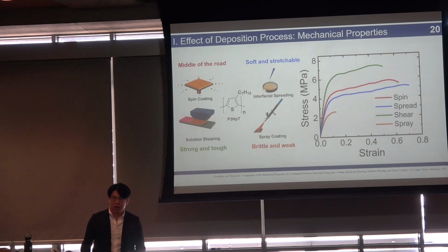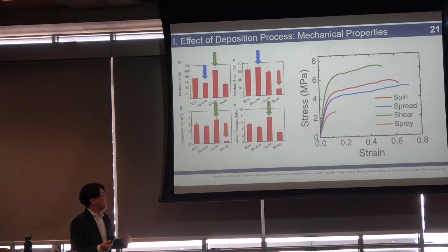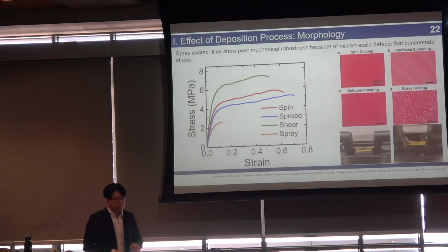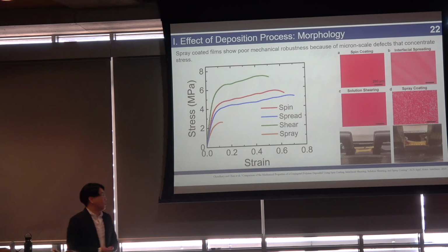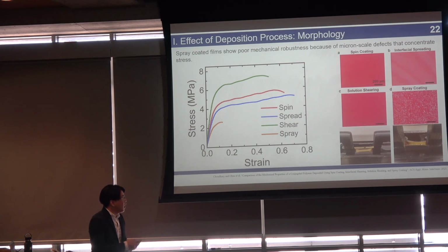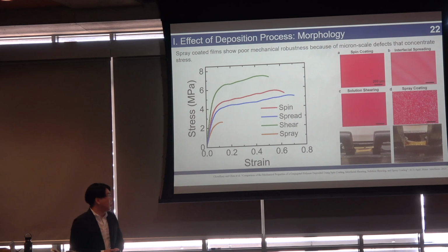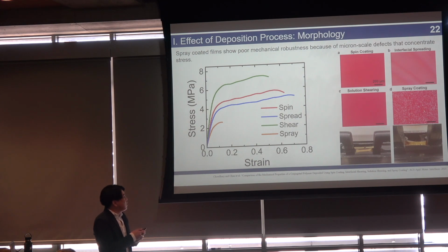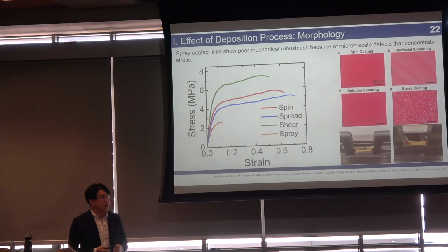So if we were to numerically extract these values from our plot, it looks something like this. But because no one wants to read through this many plots, we're just going to simplify it. So immediately, we can tell what's happening with spray-coated films if we just look at these films under the microscope. Spray coating causes this granulated sort of microstructure, and you can actually sort of see that in this dog bone below. And this granulated microstructure concentrates stress, and it allows for the fracture of these films very early. So this is why they're very brittle and weak.